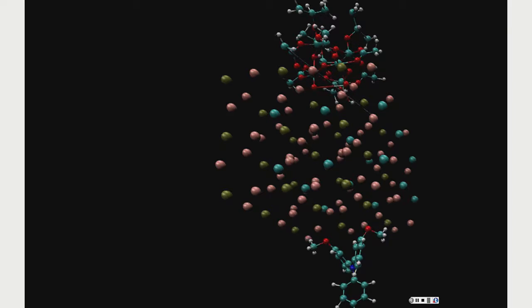Is there a way for me to do that in VASP? No, there's no way. I'm saying it's just a conceptual problem with this approach, because in the classical limit you take your energy and divide it over the number of atoms, roughly over oscillators. And roughly speaking, the average energy for each oscillator would be this amount. But in reality, this approach will be applicable only for your middle part. For the other ones, they should actually get only the energy equal to their h nu, which should be at a level of 1000 something, 500, which is much lower than kT.